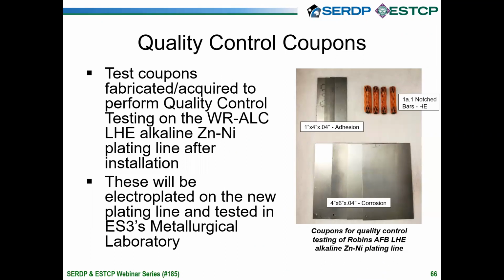So these are just the quality control coupons we intend on plating next week. The testing for them will go quickly. The top left of the picture are the bend to break adhesion coupons. The notch 1A1 from the ASTM F519 specification of the hydrogen embrittlement coupons, and then the corrosion coupons that will run through ASTM B117 testing. So we're going to plate duplicates of everything at Robins Air Force Base by request of the 402nd so that they can perform the testing, we can perform the testing, and then we'll get double validity, essentially, that everything is plating as it should, and we're getting the same result. You can go on to the next slide.